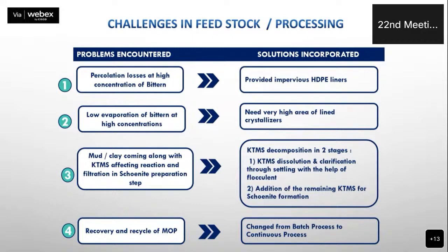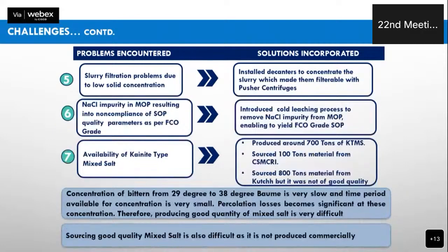Then recovery and recycle of KCl, that is muriate of potash. We changed the process from batch to continuous. So the mother liquor coming out from the first step was processed, KCl recovered and recycled back into the next step of sulfate of potash process. Then we encountered the slurry filtration problem due to low solid concentration. So we installed decanter to concentrate the slurry so that it can be filtered with pusher centrifuge. Then while working on this, we got higher concentration of sodium chloride in potassium chloride. So we introduced one step, that is of cold leaching to remove sodium chloride from muriate of potash, and then it was recycled back.